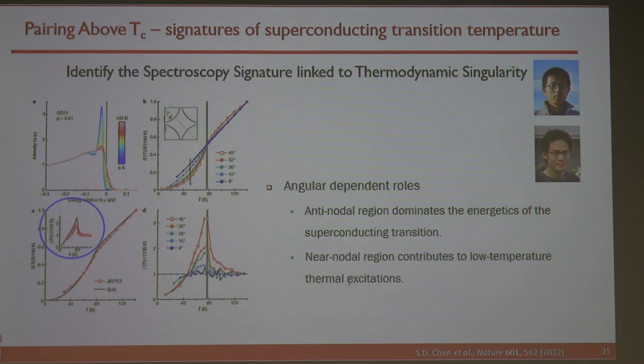Because once you know that, what photoemission can give you is the angular dependence. Okay? You can see that at the antinode, the singularity is big. As you go towards the node, the singularity gets smaller and smaller, eventually not there. That's exactly what you would have expected with a phase fluctuation model in a d-wave superconductor. So we now know we have normal state pairing. The TC was determined by phase fluctuations in that system.